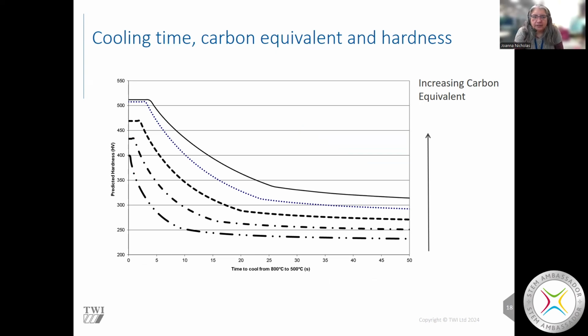That cooling time, carbon equivalent and hardness can be related by looking at different rates. So we've got that cooling time and some hardness on the graph, with increasing carbon equivalent as we go upwards. So you can see that as we increase the carbon equivalent, the value of the predicted hardness goes up for the same cooling time. So if I want a particular hardness, I need to choose a lower carbon equivalent or a longer cooling time, depending on the actual conditions I've got.